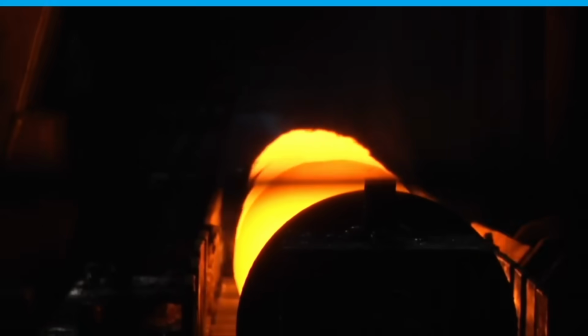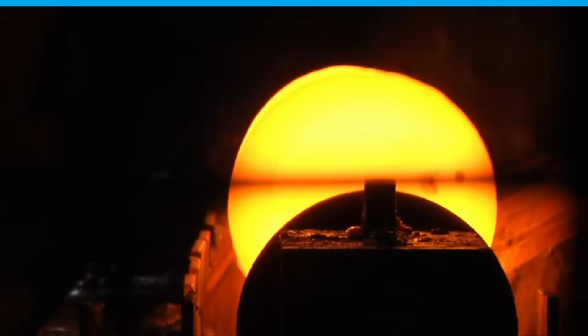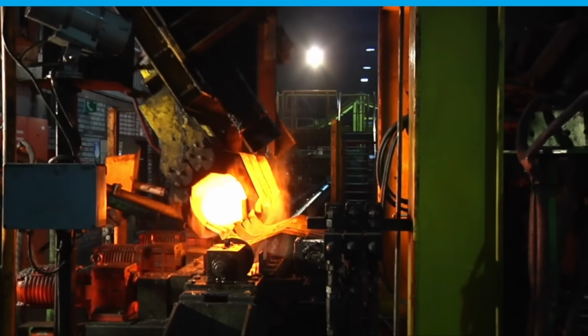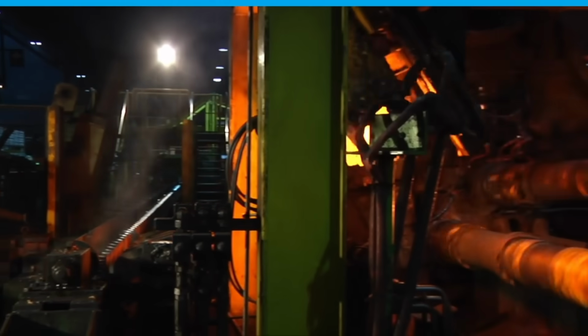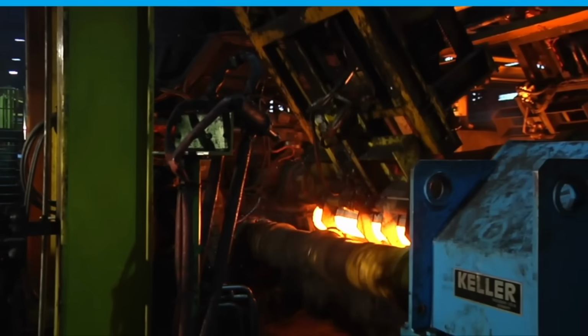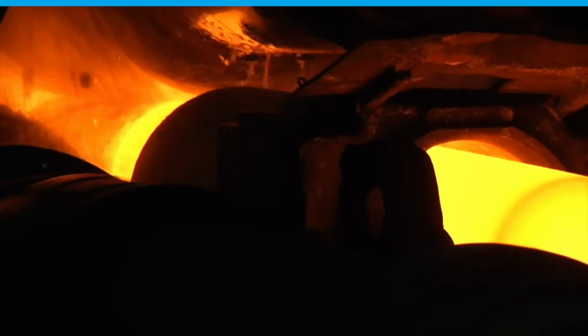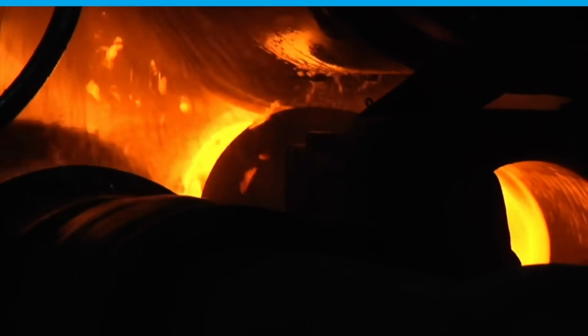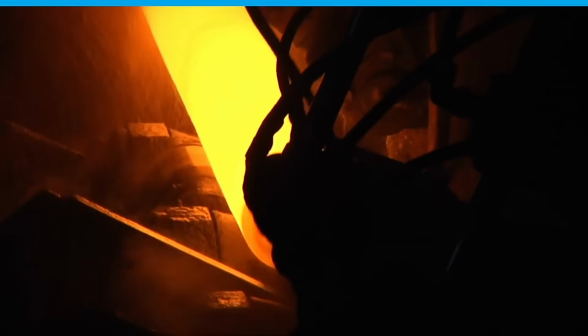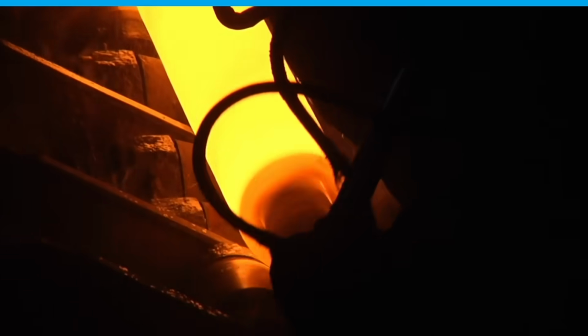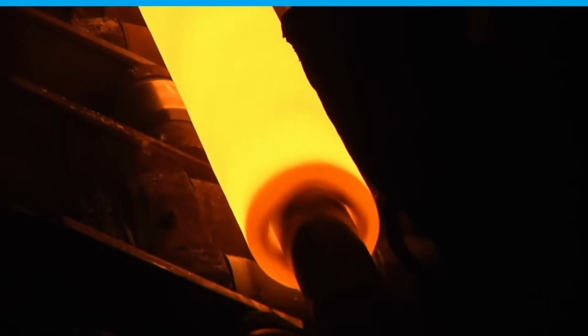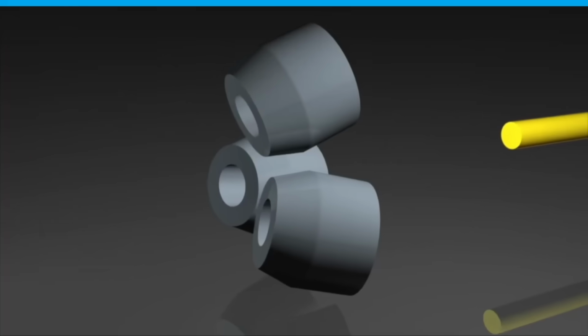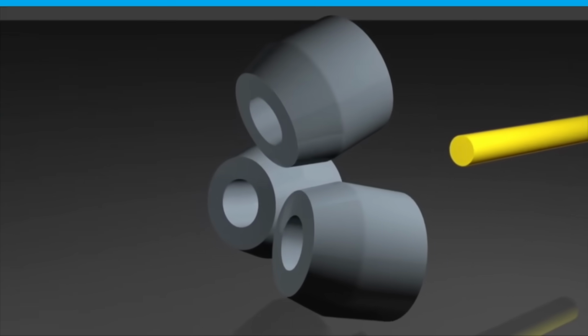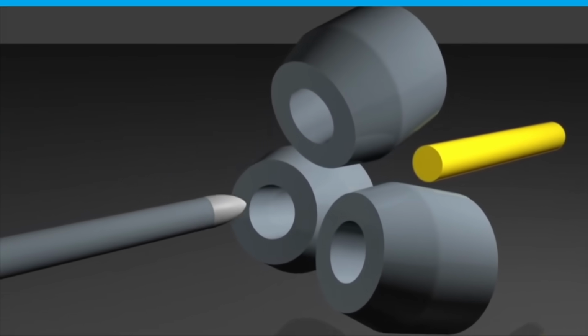Once heated, the billet enters the piercing stage, where it undergoes the three-roll cross-roll piercing method, an advanced evolution of the Mannesmann process. The billet is rotated and simultaneously compressed by a 40-ton force against a mandrel that forms the tip of a water-cooled holding rod. The rollers grip the billet and set it in a rotating movement. The rollers are set at a defined angle to the longitudinal axis of the mandrel bar.